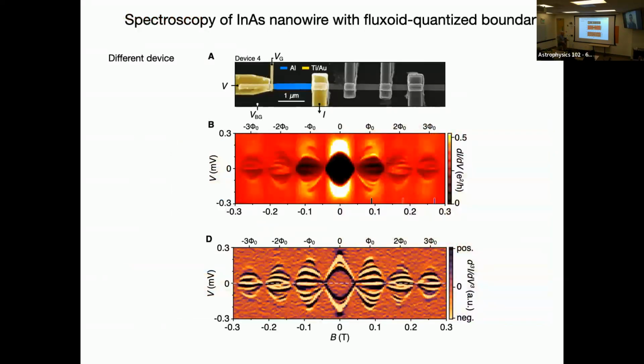And it's interesting also to see, and this is experimental data, and it's true in the cylindrical case perfectly, that it's an odd number of twists of the wave function that you need. If the wave function evolves by 4π around the rim, then you get Caroli-de Gennes-Matricon states, but not a state at zero. Only when you have 1 twist, or 3 twists, or 5 twists.